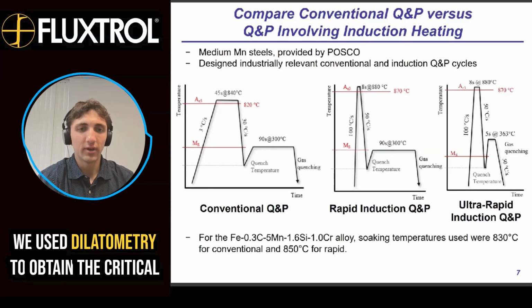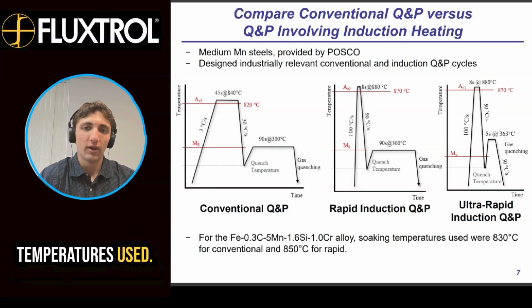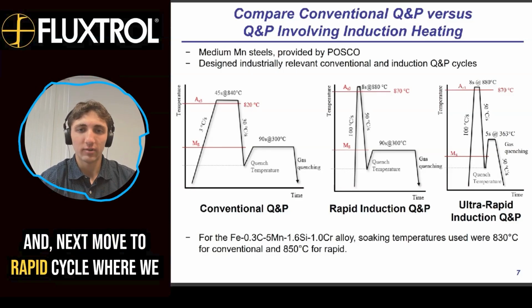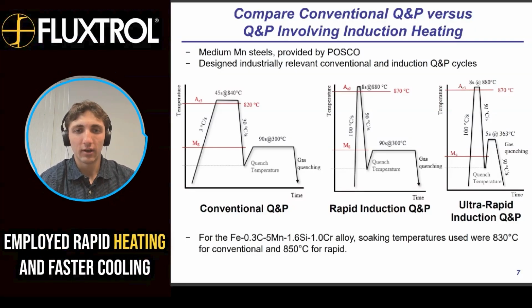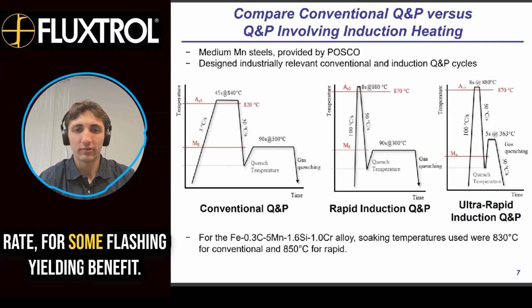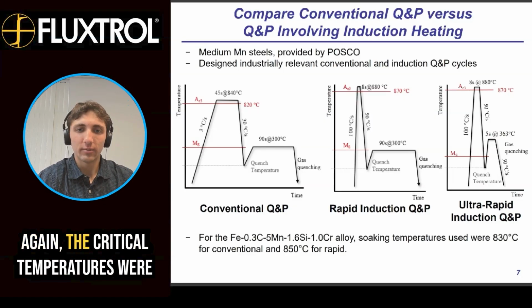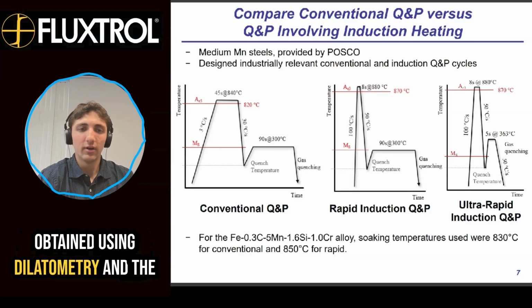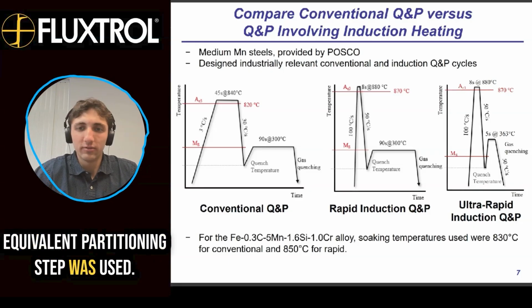We used dilatometry to obtain the critical temperatures used. Next, move to rapid cycle, where we employed rapid heating and faster cooling rate for some flash annealing benefit. Again, the critical temperatures were obtained using dilatometry, and an equivalent partitioning step was used.